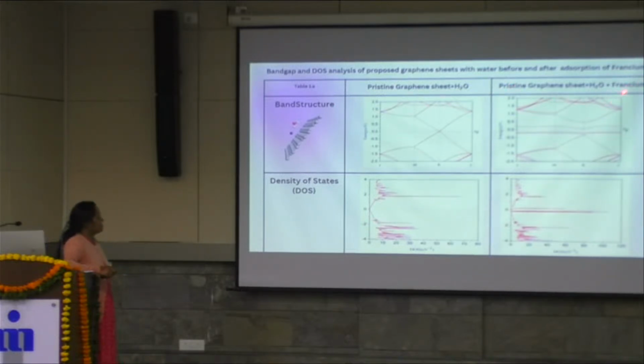But then we found a change similar to the previous radium in the francium. When we introduced francium, there was a change in the band gap. There was some indirect band gap present when we kept an atom of francium near the graphene sheet. Similarly, we found a change in the density of states also. The electron states have increased near the Fermi level, but the band gap was present in this case.